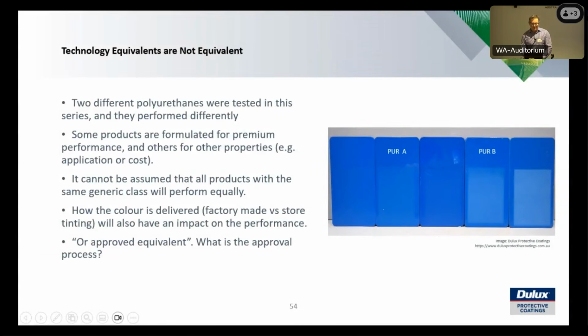Although I mentioned we tested 4 coatings, you're wondering why there's 5 panels up there. We put 2 polyurethanes in there, and they both performed differently. So it's really a case in point where equivalents aren't equivalent. A lot of the time we will see on architectural schedules or other specifications an 'approved equivalent'. Sometimes what might be said as an approved equivalent might not perform as an approved equivalent. And the result may be similar also if we provided 2 polysiloxanes in the test or 2 fluoropolymers as well. You might get some quite larger variation. It's just that for this test we chose 2 polyurethanes.